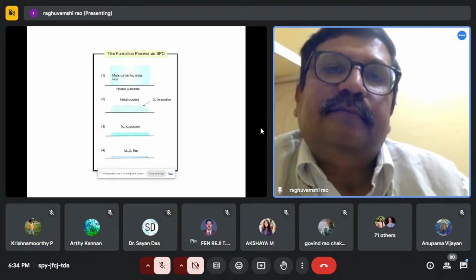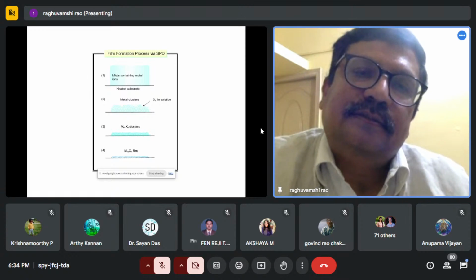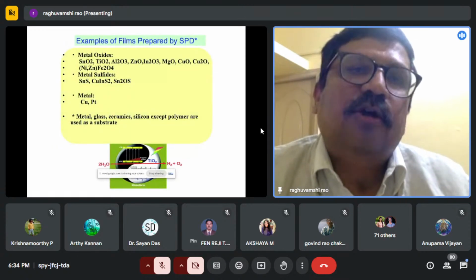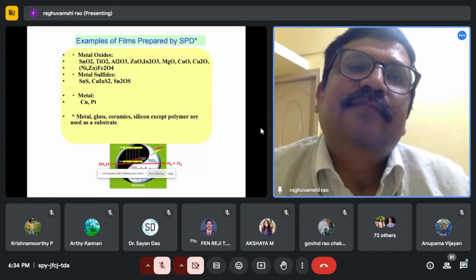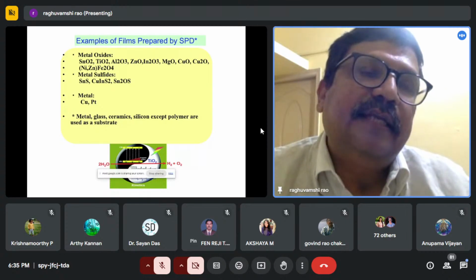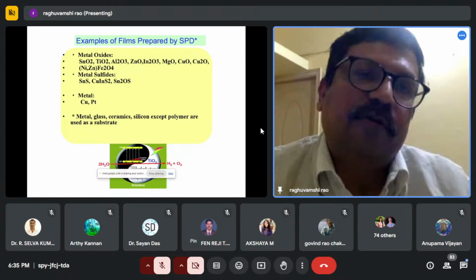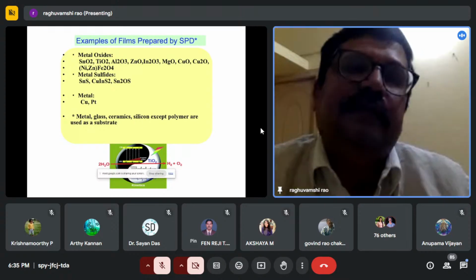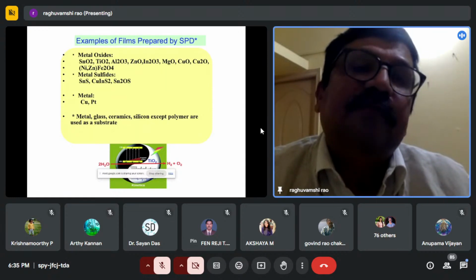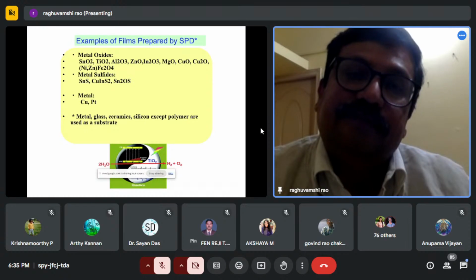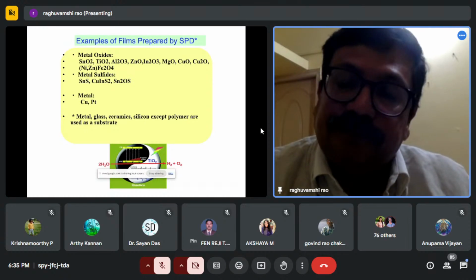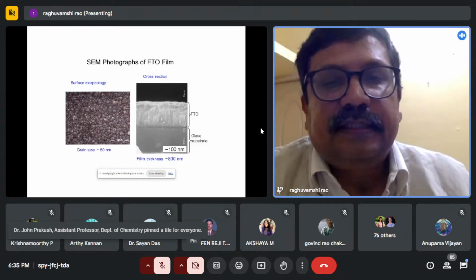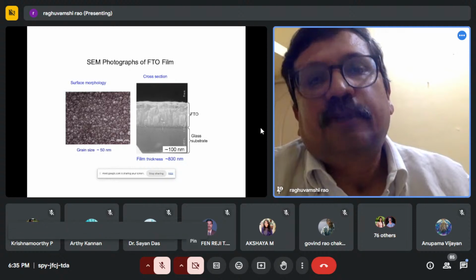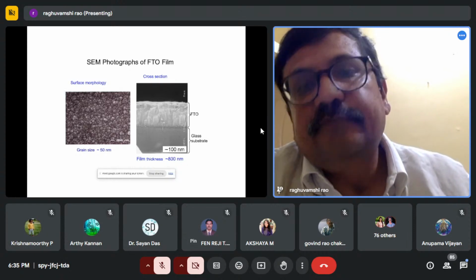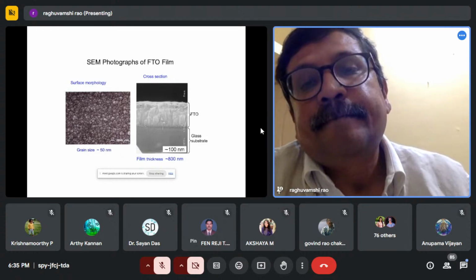It can be worked with metal clusters, different types of films can be formed, metal oxides, tin oxide, titanium dioxide, then different types of metal sulfides, metal per se, copper and platinum. We have worked with platinum precursors, which we got from Japan, and then it was used in our units here. Different types of substrates can be worked with: metal, glass, and ceramics, except polymer because of the temperature issues there. These are some SEM photos and cross-sectional morphology after the FTO was coated using the spray pyrolysis technique.